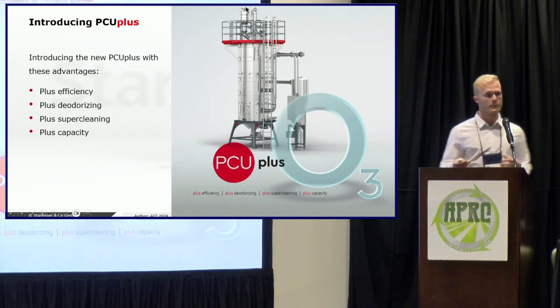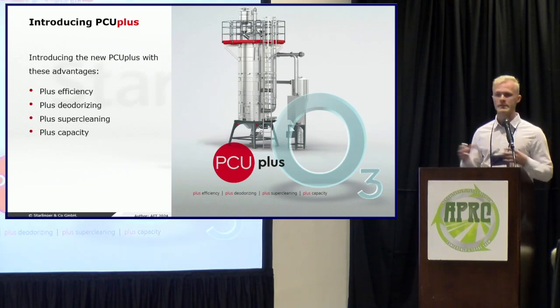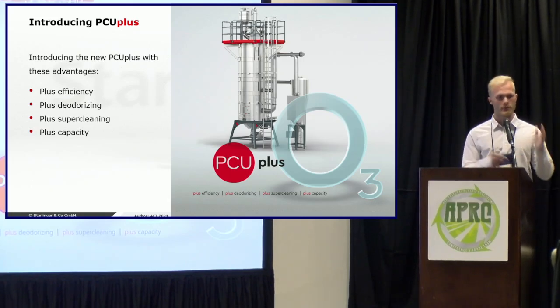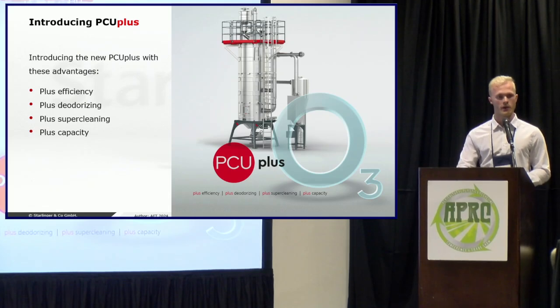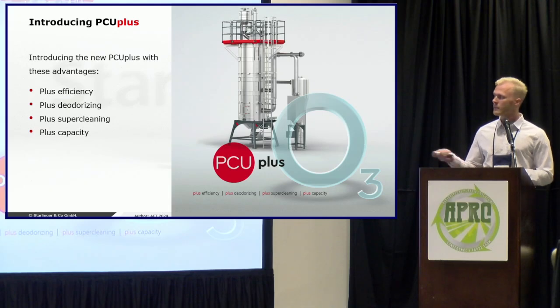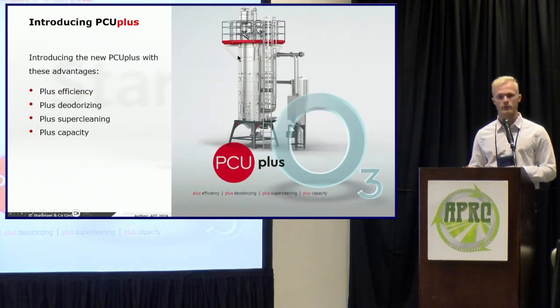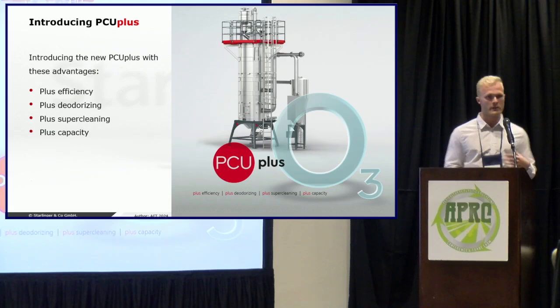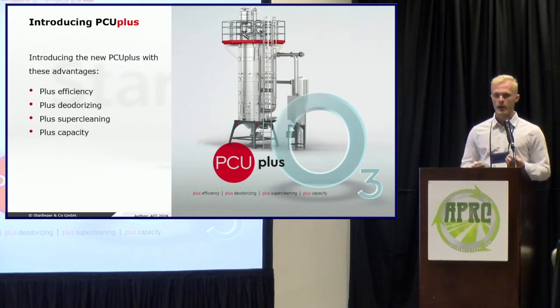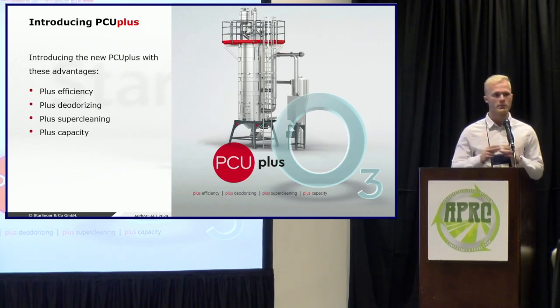And the way that this system works is the pellet will actually enter into the top, which is a preheater. So each customer who gets a PCU Plus of ours will receive an oven with the unit. And this is important because you want to batch test whatever material you're running that day to see what the softening point is and what the melting point is of the polymer. And once you do that, you want to set the process conditions in the actual vessel to be 3 to 5 degrees Celsius below that softening point. And this is going to allow the contaminants, the VOCs, to actually migrate to the edge of the pellet.